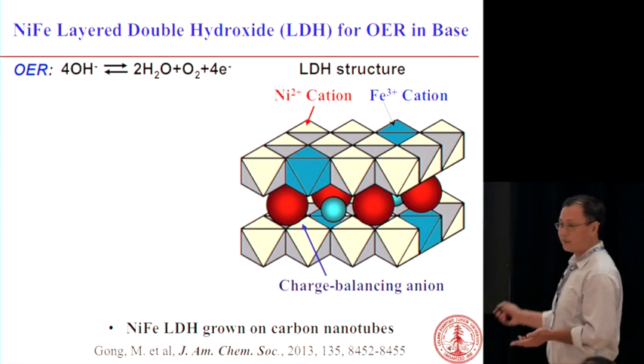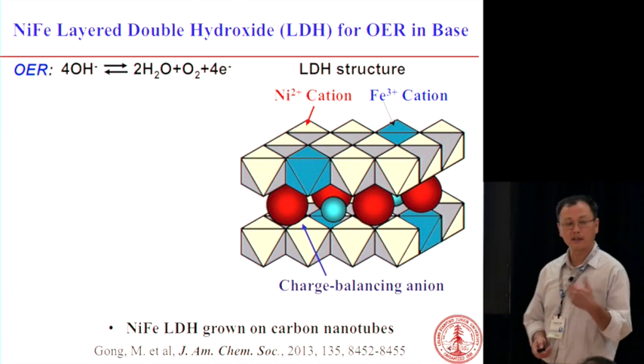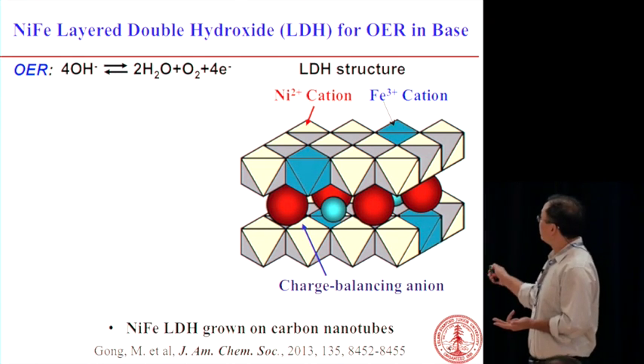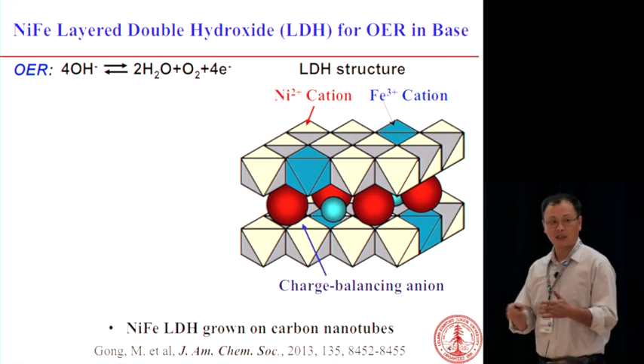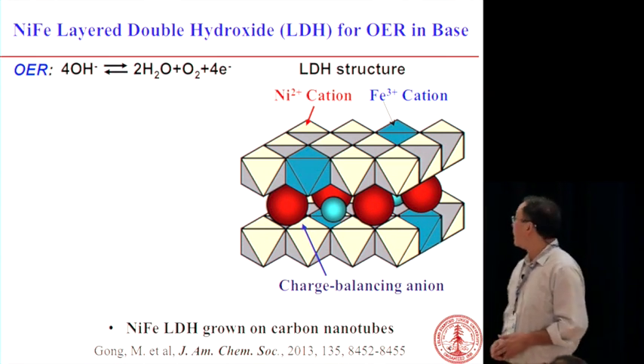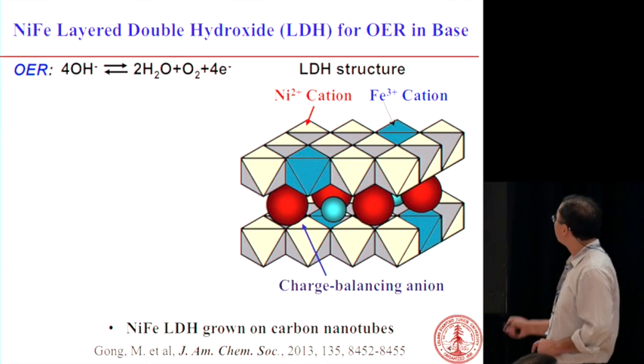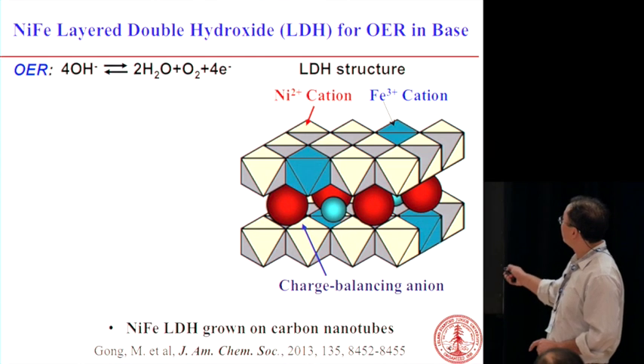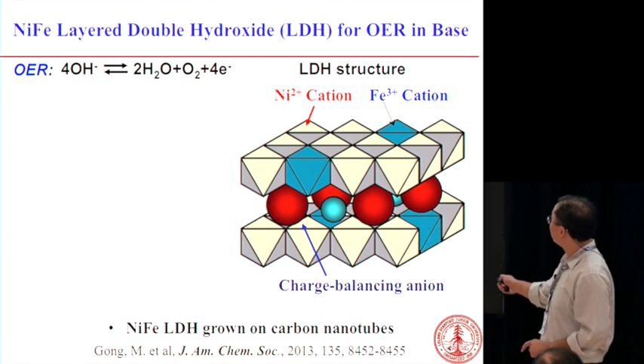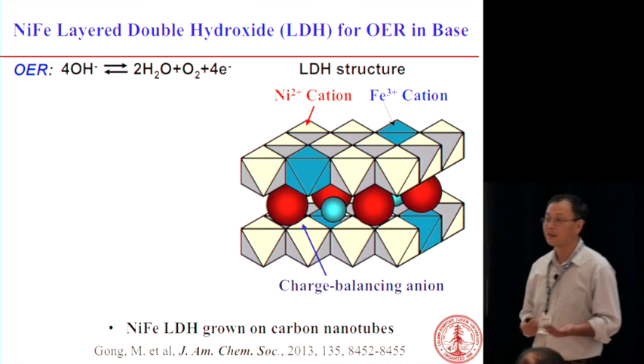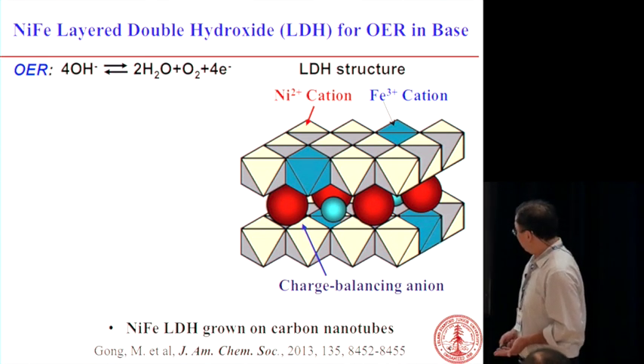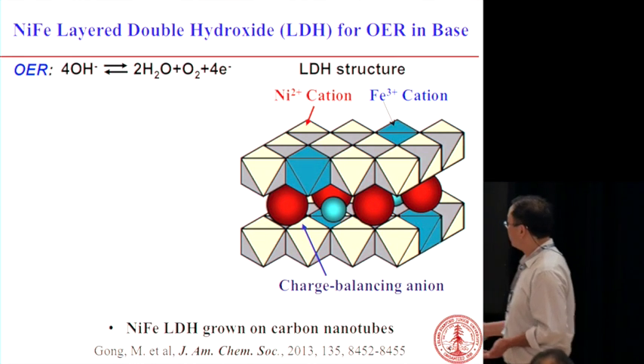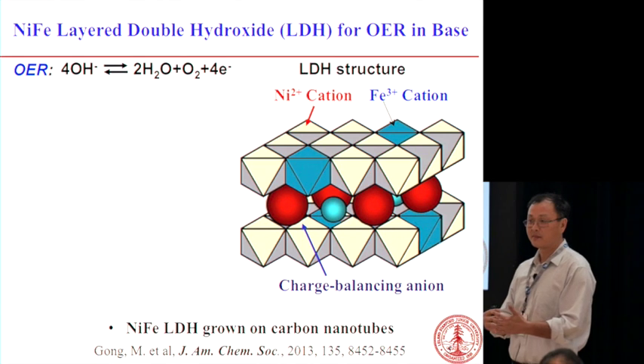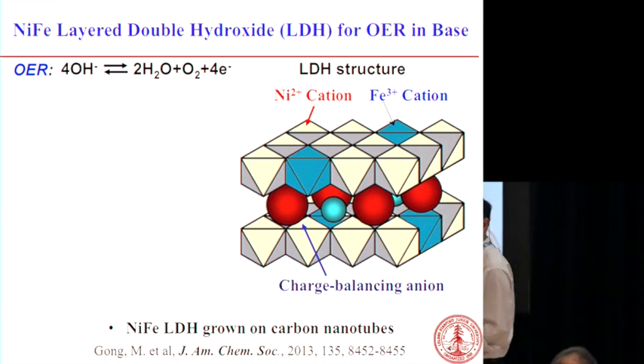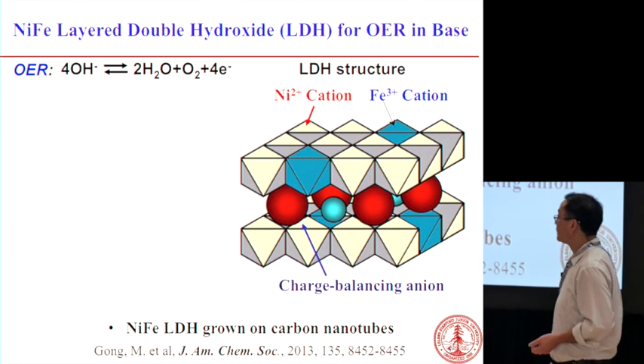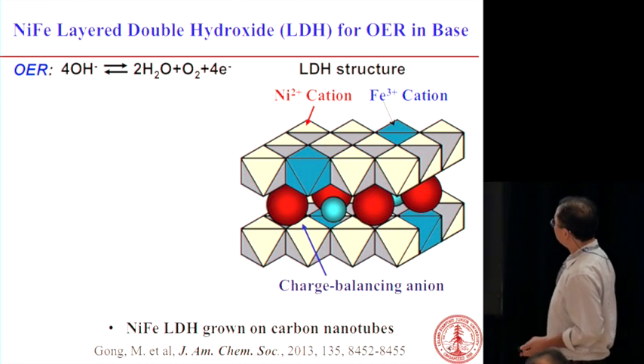So this really is like, if you're familiar with graphene, it's very similar to that, but it's an inorganic version of it. So you have these sheets of hydroxides that are stacked together, and you can make very thin plates of them. And you see these octahedrons really just have nickel in the middle, or some of them would have iron 3+ in the middle as dopants, okay? So these plates were grown on carbon nanotubes because we would like to have a network of carbon so that the material is very conducting, so it gives us even better activity.